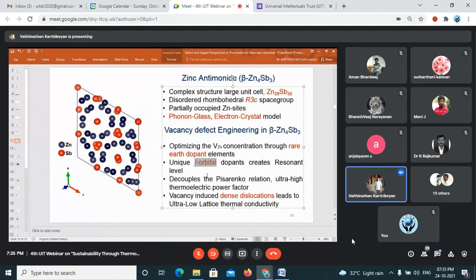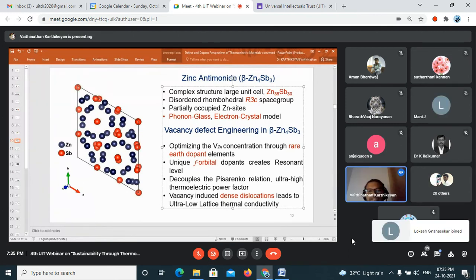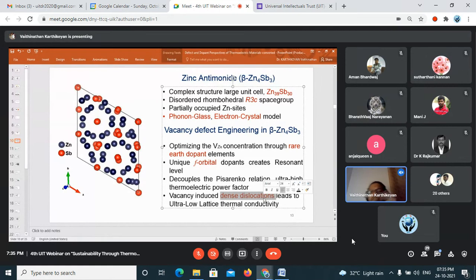The uniqueness of why we use the rare earth dopants is that they have f orbitals, whereas other groups do not have them. This is a good advantage, as they can create anomalies in the material. So we want to try with the rare earth dopants. And we found that it decouples Seebeck and electrical conductivity and causes a parallel increase in Seebeck and electrical conductivity. And also it creates very dense defects in the lattice, which causes the lifetime of phonons to decrease.